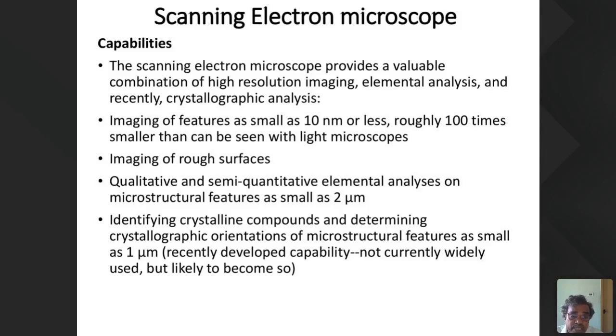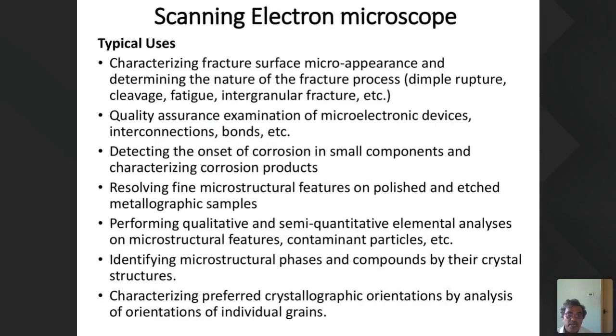What are the capabilities? The scanning electron microscope provides a valuable combination of elemental analysis and crystallographic analysis, with features on the order of nanometers, roughly 100 times smaller than a light microscope, and imaging of rough surfaces. You can also do surface roughness and nano surface metrology. It gives qualitative and semi-quantitative elemental analysis of microscale features on the order of 2 microns, identifies crystalline compounds, and determines crystallographic orientation as small as 1 micron. Typically you can also see dimple rupture, cleavage, fracture, fatigue and intergranular fracture.